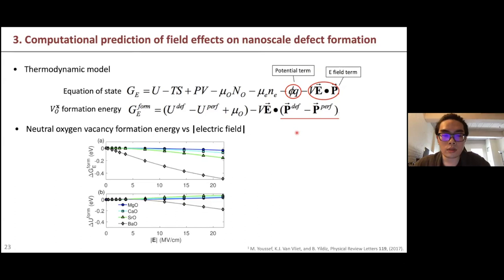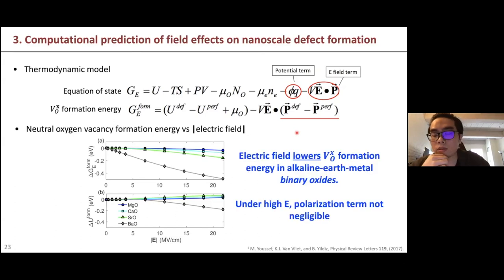However, here the electric field in a memristor is very, very high, and this term becomes non-negligible, and it will be comparable to the potential term. Previously, Dr. Yusuf studied the electric field effect on the neutral oxygen defect formation energy, and basically this term is very important. It is the difference of the dipole moment P between the defected cell and the perfect cell.